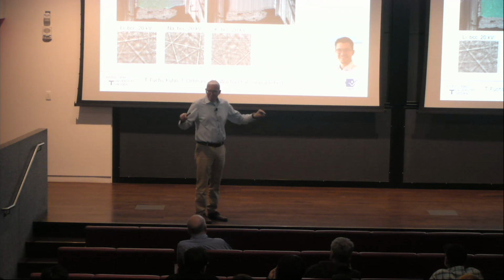Let me answer with a paper, not from us, but from Matt McDowell at Georgia Tech. They have a nice paper probably coming out soon, which is already available on ChemRxiv, where they show that a not too thin sodium interlayer for lithium electrodes very much improves the kinetics. They prepare lithium foil with a lot of sodium inside, forming sodium particles, because, as I told, lithium doesn't dissolve sodium. Upon stripping, it seems to form a thick sodium layer, and sodium is, of course, softer than lithium. It seems that this soft interlayer helps keep contact and avoid forming pores.